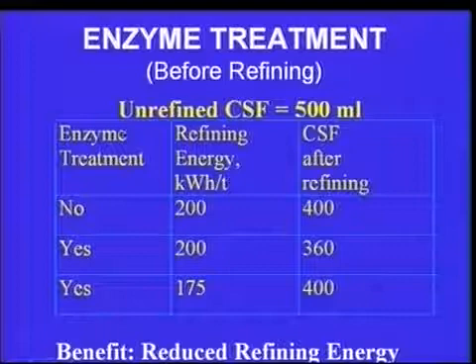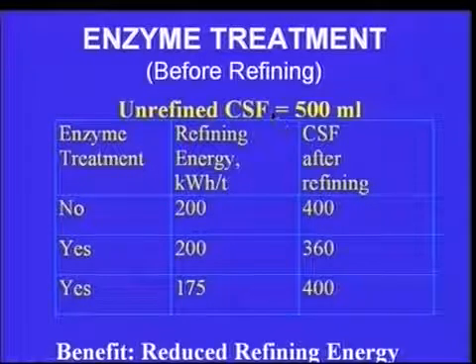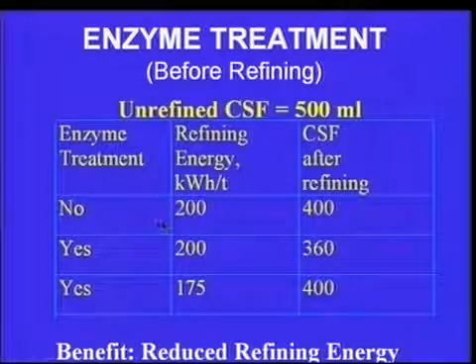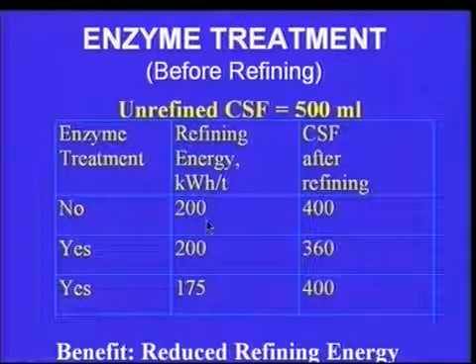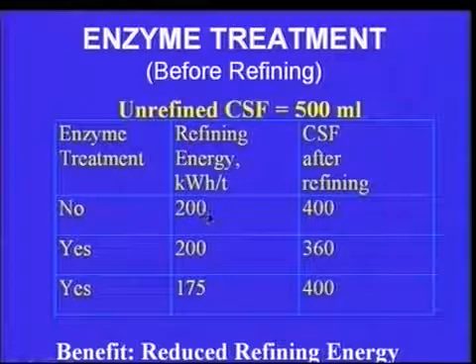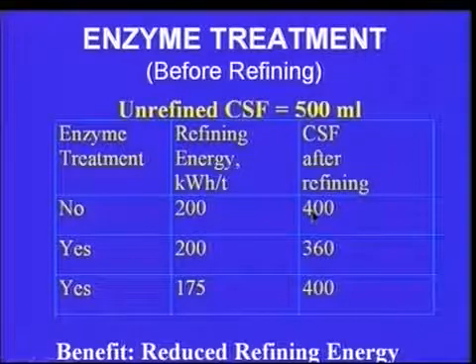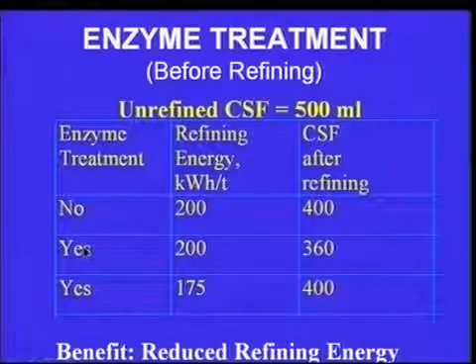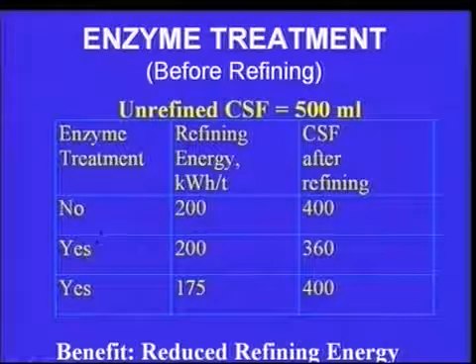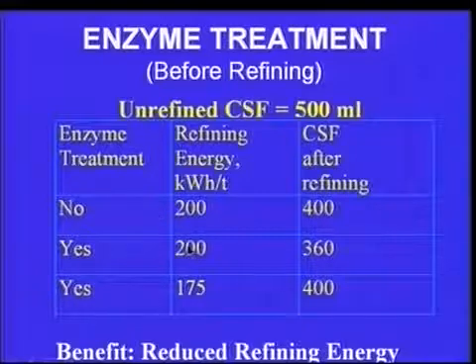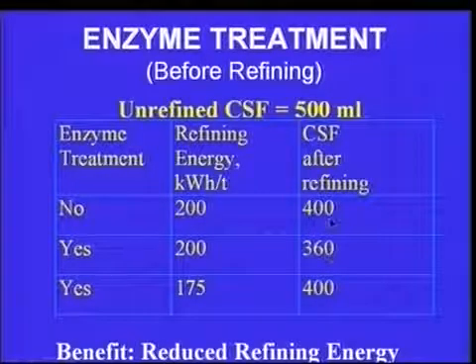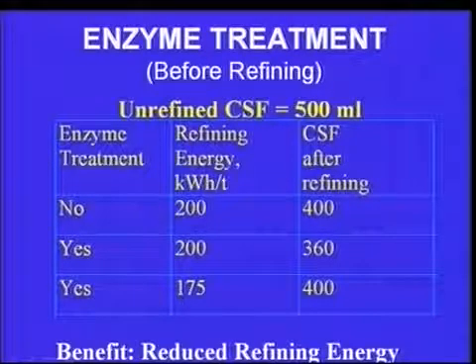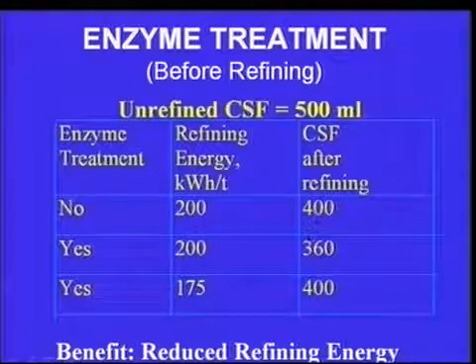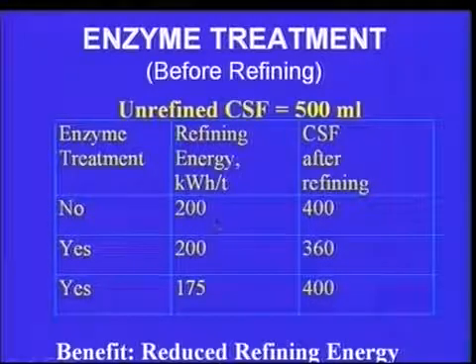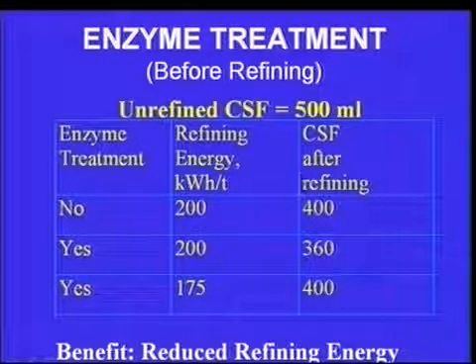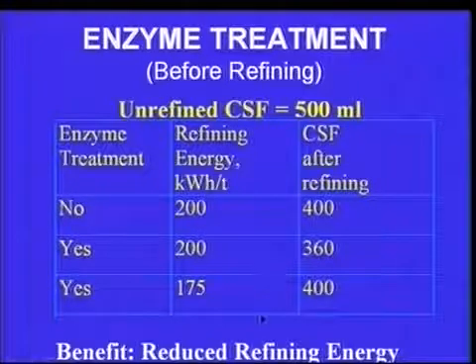Here is an example of the effect of enzyme treatment on unrefined pulp with the freeness of 500 milliliter. When you use refining energy of 200 kilowatt hour per ton and refine to reduce the freeness from 500 to 400, the same pulp following the enzyme treatment using the same energy can reduce the freeness to 360 instead of 400, or use less energy, 175 kilowatt hour per ton, to go back to the same freeness as 400. In other words, we have energy savings of about 25 kilowatt hour per ton for reducing the freeness from 500 to 400.